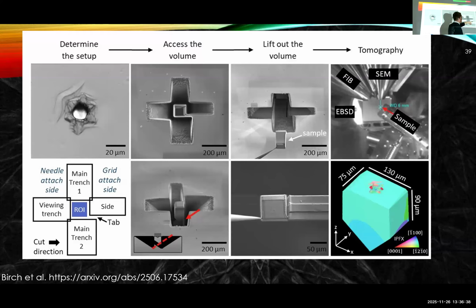The sample gets mounted in this interesting geometry, sort of sticking up here, and then we can do FIB-SEM without moving the sample between each stage. And that enables us to get out this object. In this case, it's 130 micron by 75, and then we got about 90 deep.